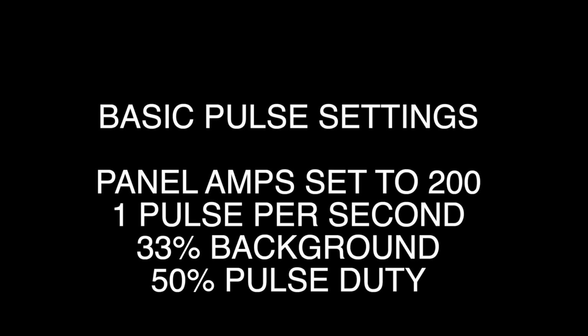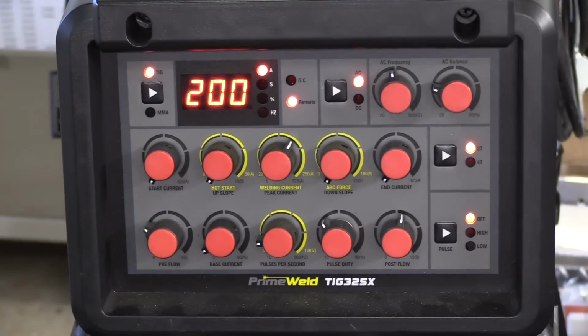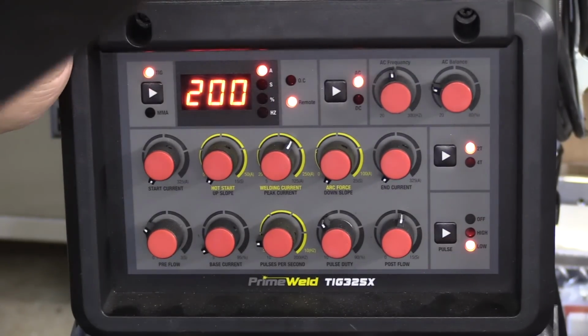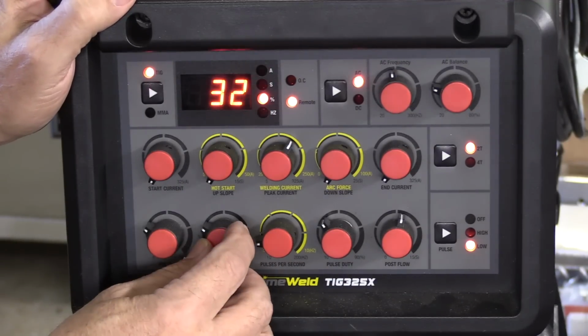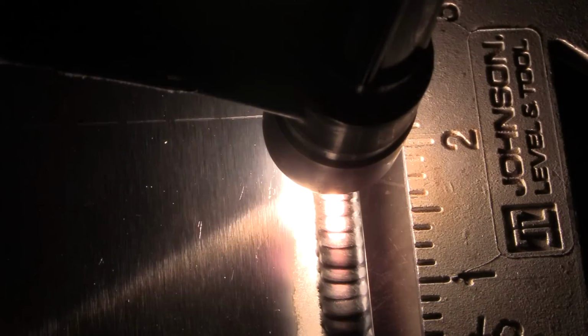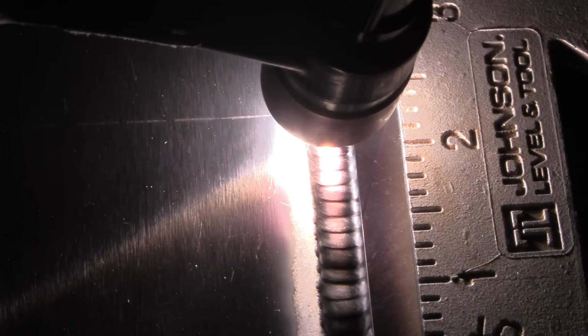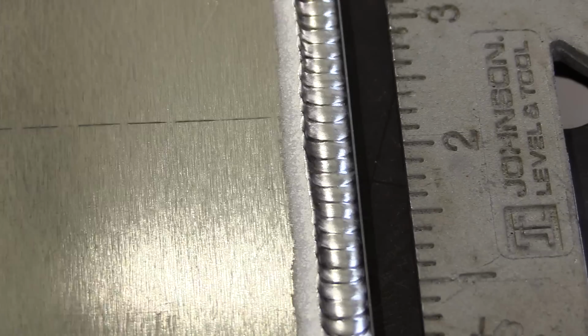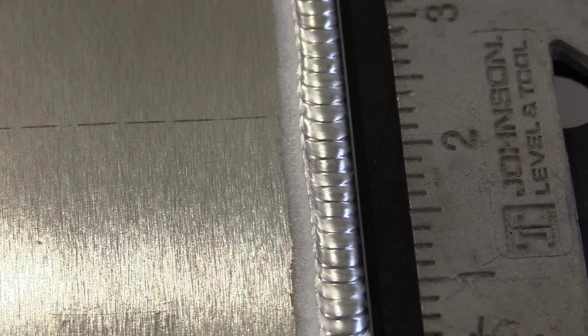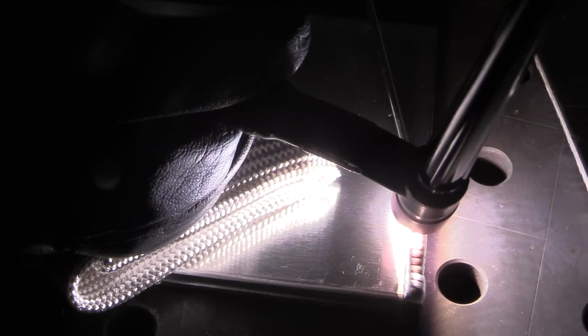Another thing that occurred to me on this job is maybe using pulse settings. So I set the machine to a baseline pulse setting of 1 pulse per second with a background current of 33% with 50% on time. And that's fine. It works fine. It gives you kind of a rhythm, but it does limit you. You can't really go much faster than 1 dab per second on the high pulse. You typically add filler wire on the high amperage side of the pulse so that it melts in there nicely. So you're limited on your travel speed when you use pulse.